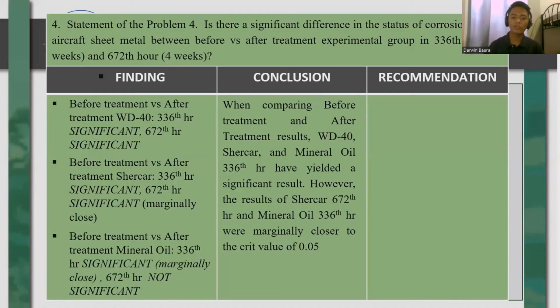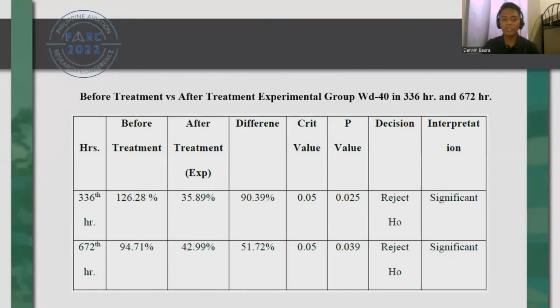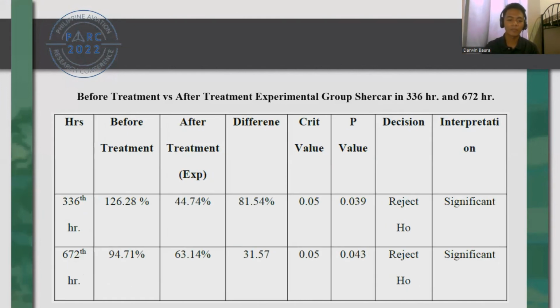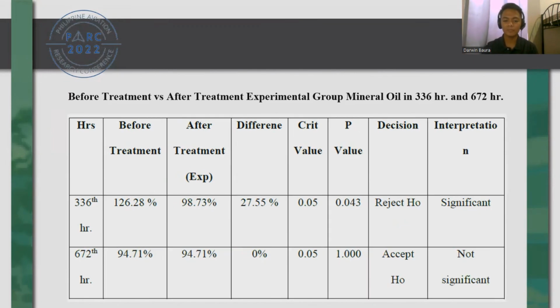Statement of the problem 4 will determine if there is a significant difference between before and after treatment using the SPSS 21 statistical software. Before treatment versus after treatment, WD-40 has an interpretation of significant at both 336 and 672 hours. This is because their p-value is lower than the critical value 0.05. Before treatment versus after treatment, Shercar still has an interpretation of significant at 336 and 672 hours. This is because their p-value is still lower than the critical value 0.05. But it is important to take note that the p-value of Shercar at 672 hours is marginally close to the critical value 0.05.